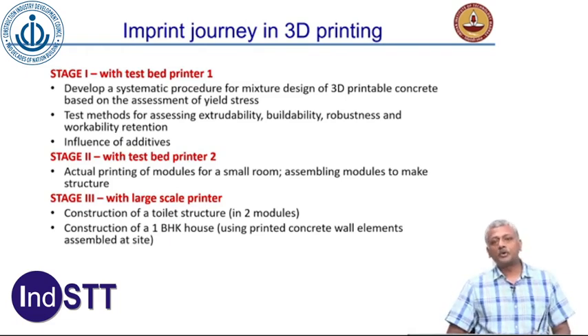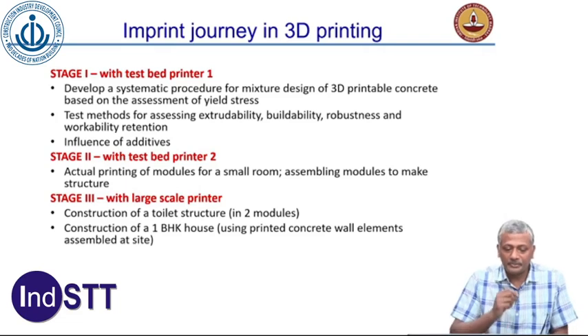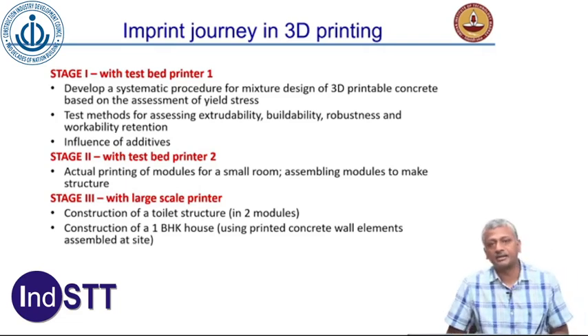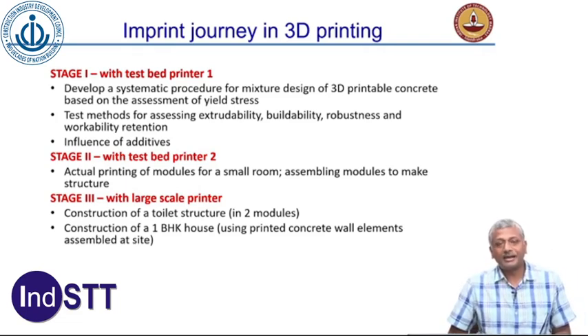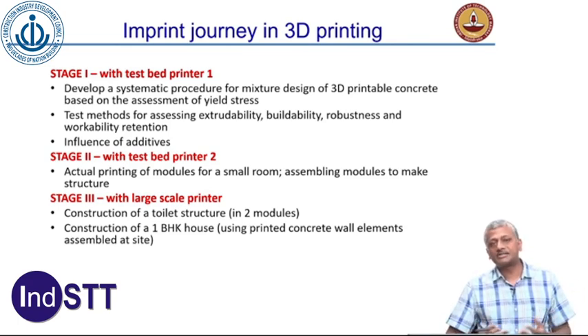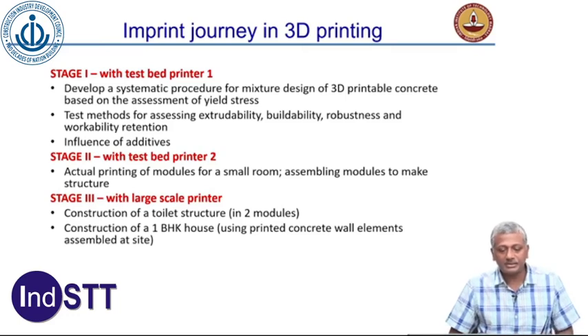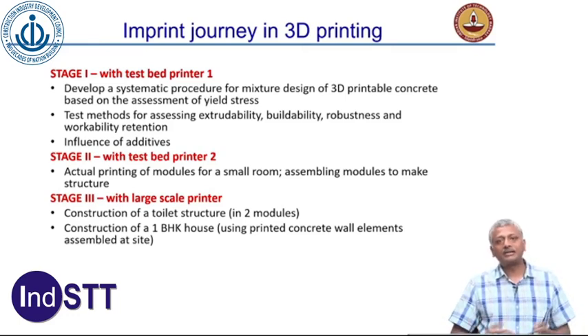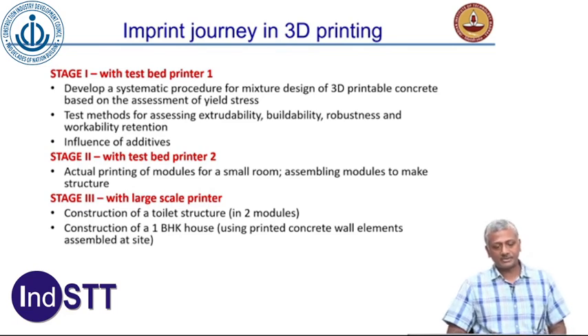So here the objective of our studies was to develop a systematic procedure for mixture design of 3D printable concrete, and then devise or adapt very clearly the test methods that can be used to define how the mix extrudes through the nozzle, how it actually builds up layer by layer, and how it actually behaves later in terms of its retention of workability and what influence do other additives have on the system.